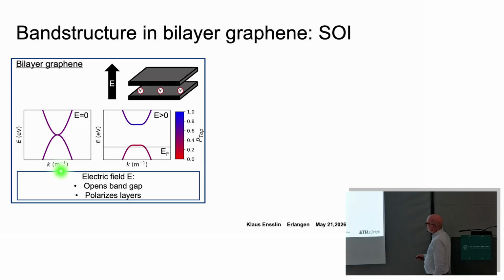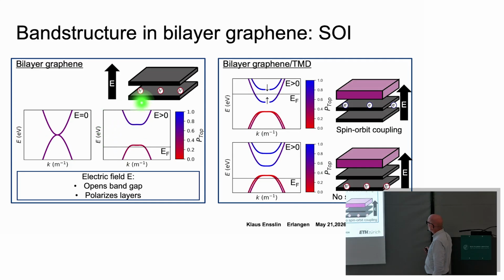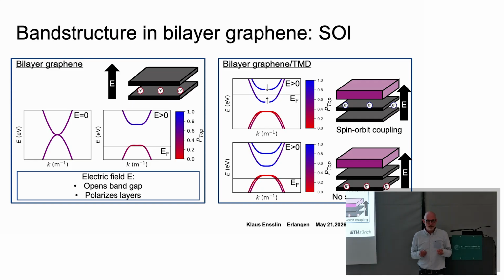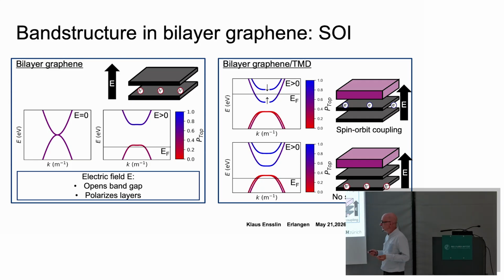So I showed you here the band structure. This is ungated bilayer graphene, two parabolas. You open a band gap by applying an electric field. Now there's another class of materials, the so-called transition metal dichalcogenides. These are all materials that you can exfoliate like graphene. Unfortunately, they are not very clean, so the electron mobility is not very good. And they have extremely strong spin-orbit interaction. It's like half an electron volt. It's a significant part of the band structure. So it's completely on the other side of graphene.